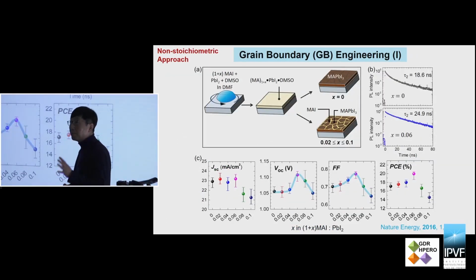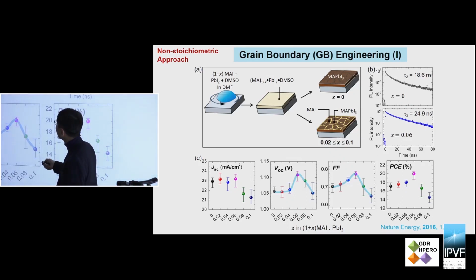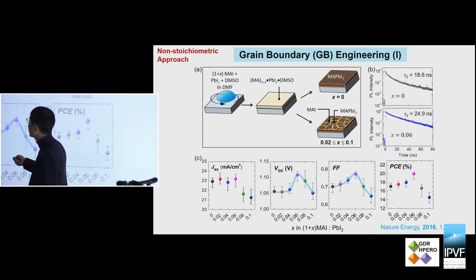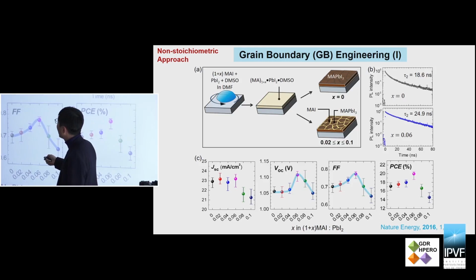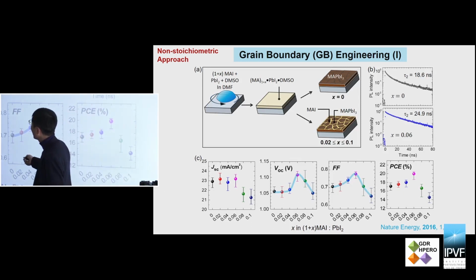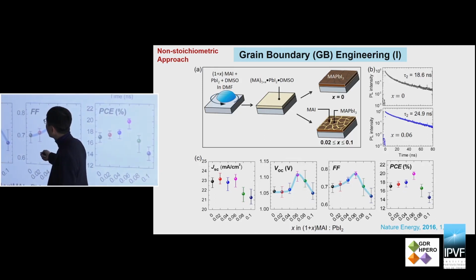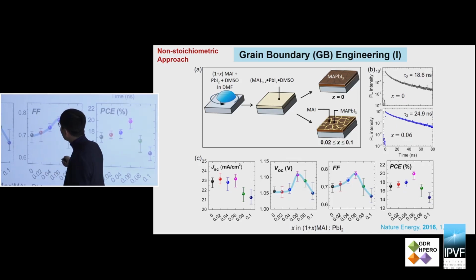And for the grain boundary engineering, there are some methodologies. One is we first introduced non-stoichiometry. It's actually the first approach. So we add excess precursor chemicals such as methylammonium iodide for the case of MAPbI3. We introduced some excess methylammonium iodide and then spin coat. And to make it, using the Lewis acid based adduct method, using this kind of intermediate, and then finally after annealing this adduct film, we can get MAPbI3.